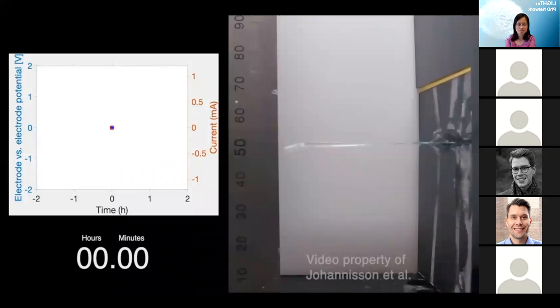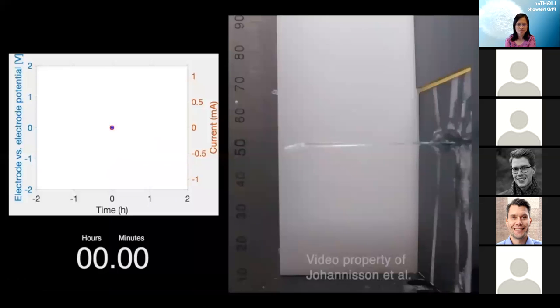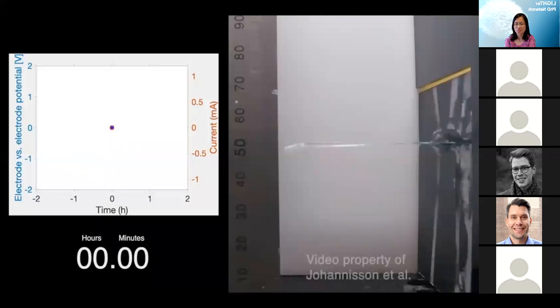We're going to see a video of this bending movement. The video is fast forward. We can see hours and minutes down here. In the graph, we can follow the voltage difference between the electrodes and the applied current as a function of time. On the right, we see the material, which is clamped on the wall at one end, and the other end is free. This is forming a cantilever beam.